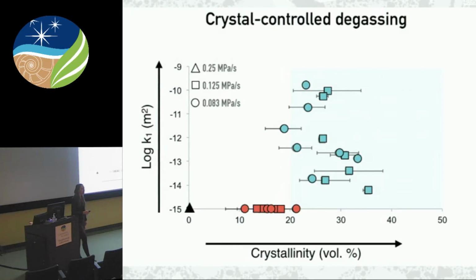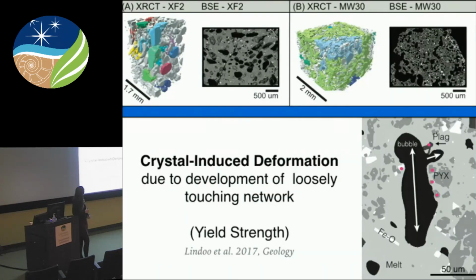Furthermore, I found that there appears to be a crystal threshold for permeability development. So looking at my samples, this is crystallinity, or volume percent crystals, on the x-axis and permeability on the y. The samples do not develop permeability unless there's about 20 volume percent crystals in the magma, and one has a crystallinity of about 16 volume percent. And the one on the right, 25 volume percent. So they're on either side of our crystal threshold.